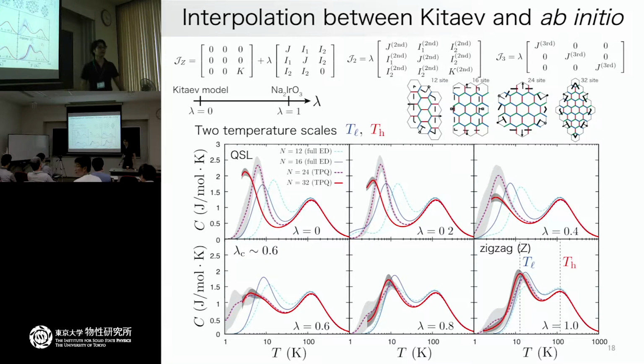How is it divided by J? J, okay, so this is 300 Kelvin. The largest temperature scale is 300 Kelvin. This is 0.3, and this is just 0.03, 0.02. I suppose it's a bit too low. No, but still, we have a small finite size effect, even then.